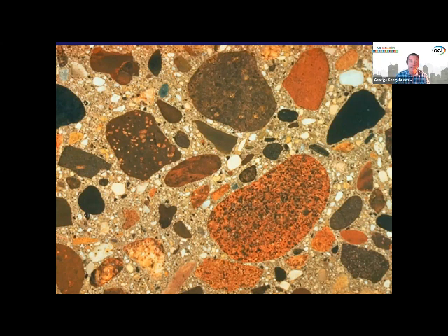I just put this slide up because I needed to take a breath. No, let's say this is a slice of a core, and let's call the top the surface of a pavement. There's two kinds of curing, external and internal. And with today's higher performance concretes, they have such low permeabilities that the cure zone is really just at the very surface, say 4 to 8 millimeters, maybe more, 10. But down below in the body of the concrete, that cure water does not really reach down there to bring along your maturity.